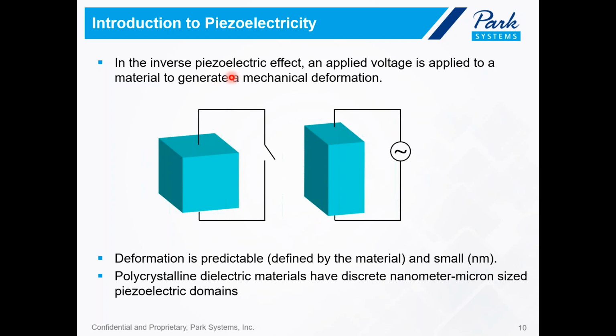So in the inverse piezoelectric effect, you apply a voltage to the material, and then this material will have a mechanical deformation in response to the applied voltage, meaning that after you apply this potential or this bias, the material will contract or stretch out based on the applied bias. And this inverse piezoelectric effect is what we monitor in piezoelectric force microscopy, or PFM.